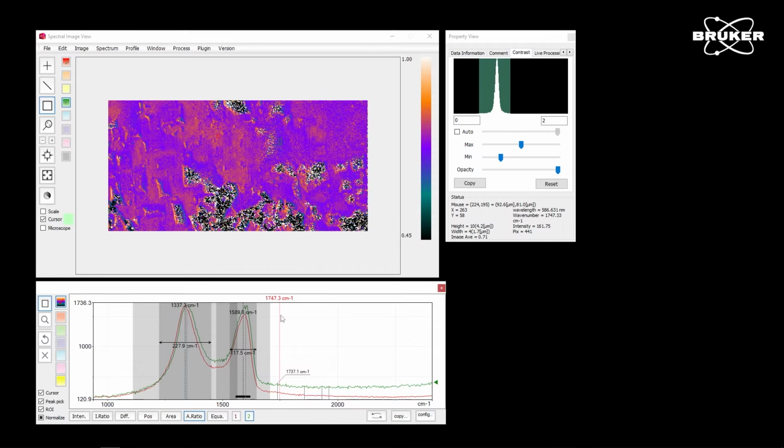And if we would result in values between 0.1 and 0.3, we would have a highly crystalline graphite. But since we end up between 0.8 to 1, more or less, we have a medium crystallinity, and everything that would be above 1, you would end up with a more poorer crystallinity of the graphite.